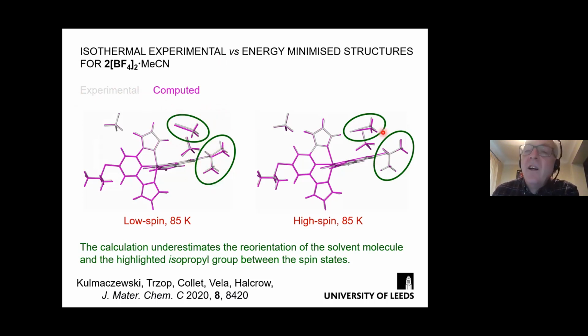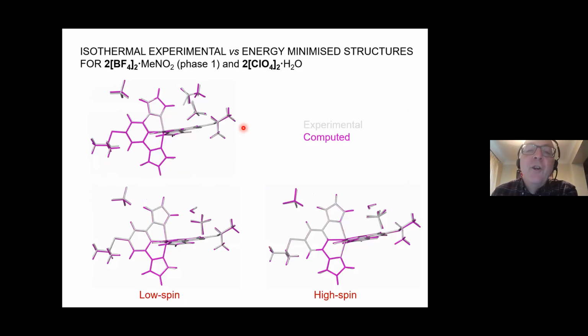The differences are in the disordered part of the crystal lattice. So this is the solvent, this is the anion, which is often disordered, and this is the isopropyl group, which is often disordered. And the orientations of these groups are not calculated correctly by this DFT. And if you compare this with 2 of the other compounds, for example, the calculated structures in this part of the lattice are much more accurate, are much closer to experiment.